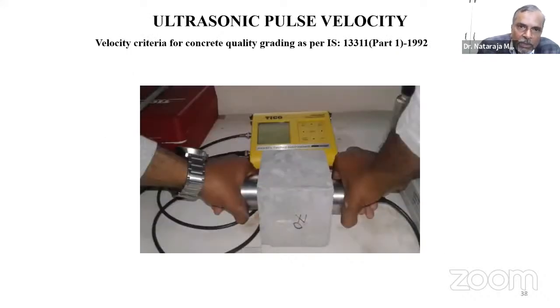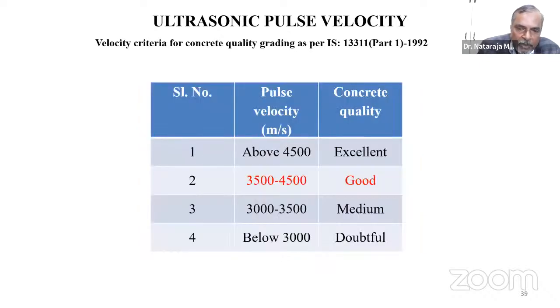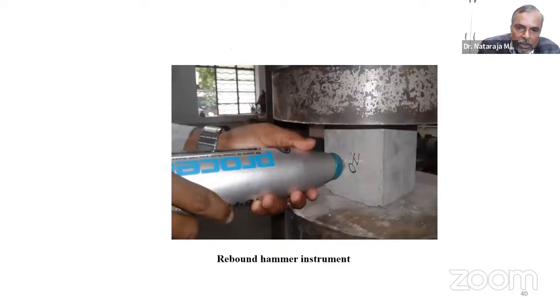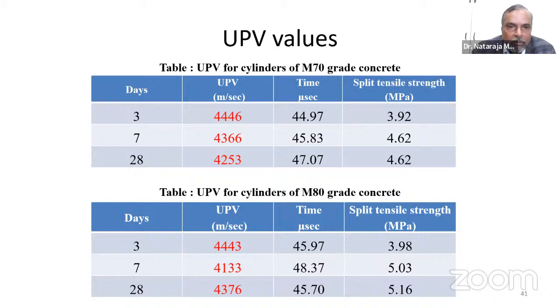Of course, you also have done some NDT tests from the point of quality assurance. So this is where the ultrasonic pulse velocity. Kindly see the range as far as the Indian code 13311 is concerned. So 3,500 to 4,500 is a very good concrete. And this is the rebound hammer value. And kindly see our ultrasonic pulse velocity value.